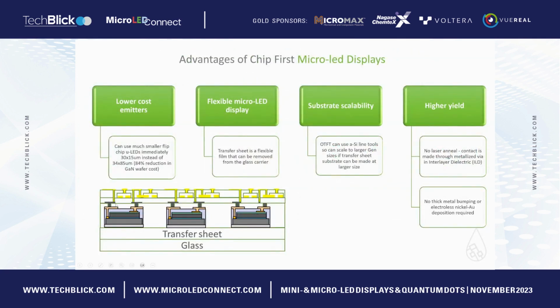Because we're forming sputtered vias and using photolithography, we can go down to very small LEDs very quickly. So in the current MicroLED TV, the LEDs are something like 34 by 85 microns, and just going down to something like 30 by 15 flip chip would be a reduction in area of 84%. So that would then give you an 84% reduction in the cost of your gallium nitride wafer.